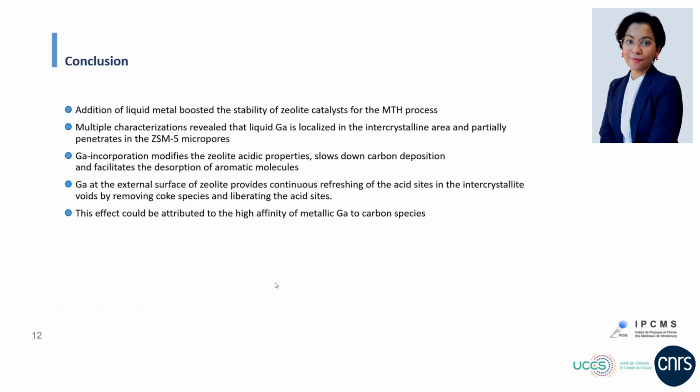So with that, I would like to come to the conclusion, as I have shown you, that the addition of liquid metal boosted the stability of zeolite catalyst for the MTH process. We have carried out multiple characterization techniques as well as DFT calculation, which I haven't shown, that reveal that the liquid gallium is localized in the intercrystalline area and partially penetrates in the ZSM5 micropores. And the incorporation also modifies the acidic properties, as we saw from the FTIR, slows down the carbon deposition, and in some cases facilitates the desorption of the aromatic molecules.